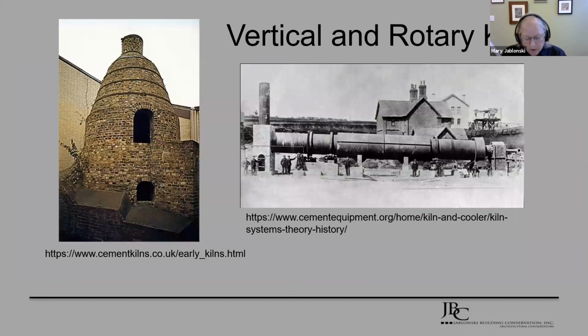Another incredible finding was that this was pre-rotary kiln Portland cement. It was European, probably French or German, not natural cement. And in the early days of Portland cement production, kilns were vertical and stationary, as you can see on the left. It was only in 1885 that an English engineer developed a more efficient kiln that was horizontal, slightly tilted, and could rotate, which you see on the right. The rotary kiln provided better temperature control and did a better job at mixing materials. By 1890, rotary kilns dominated the market.